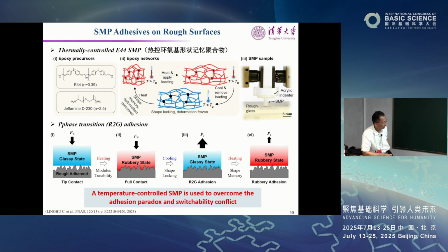Before you let go of this force, you cool it down. Now the deformation will be frozen. All the elastic energy at the interface will be temporarily locked, without release. If you now pull it, you have very, very strong adhesion. You have a super strong adhesion, right? Because the energy being stored has been frozen in the interface.